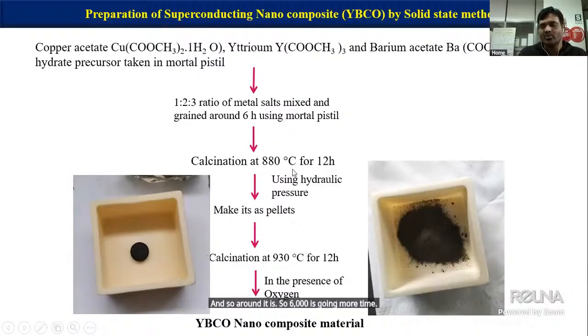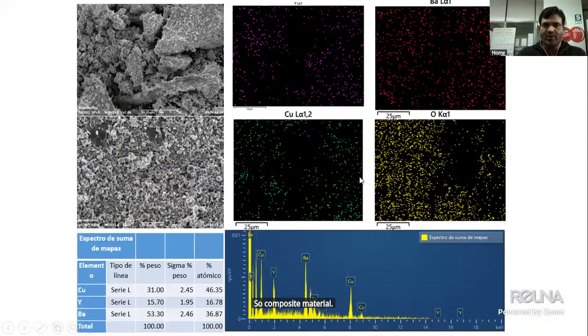Then ultimately it is calcined. Then further it is made into a pellet, then recalcined in the presence of oxygen. So we get the YBCO superconducting composite material. Further it is analyzed by SEM analysis. Here is the surface of the material. In the sol-gel method, the material is more compacted on the surface.